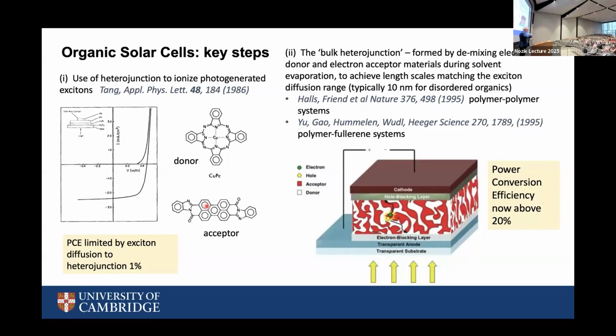And the key was to have two semiconductors, which you can just about make out in a little cartoon top left, one on top of the other, with different electron affinities. So the deal is that if we have an offset of the energy levels, this binding that keeps the electron held together in the excited state can be overcome by the electron moving from the one with the higher LUMO level to the one with a lower LUMO level, a charge transfer process, where the driving force is the lowering of energy as we move the electron from the donor to the acceptor.